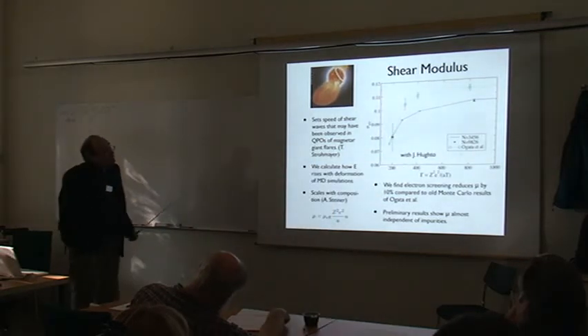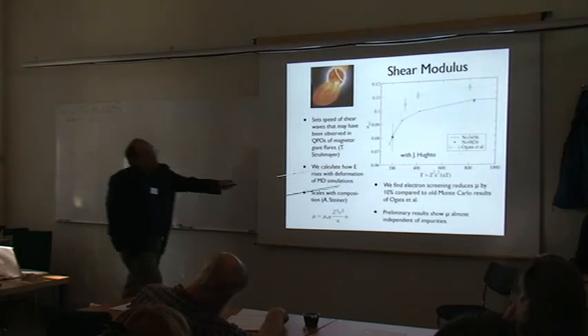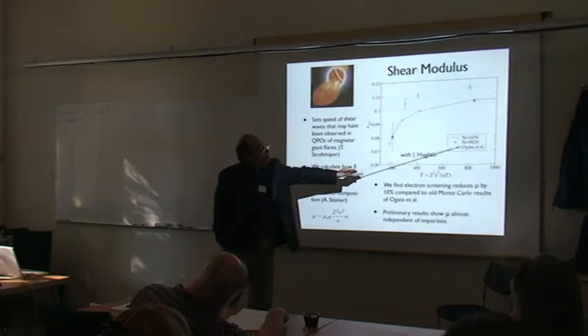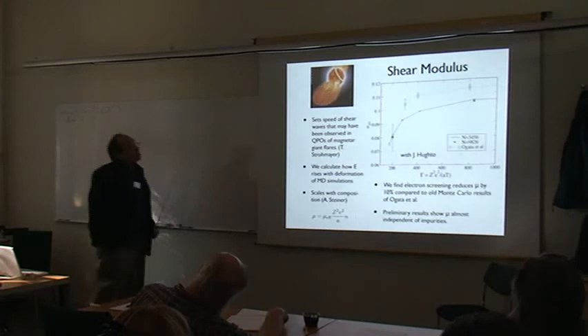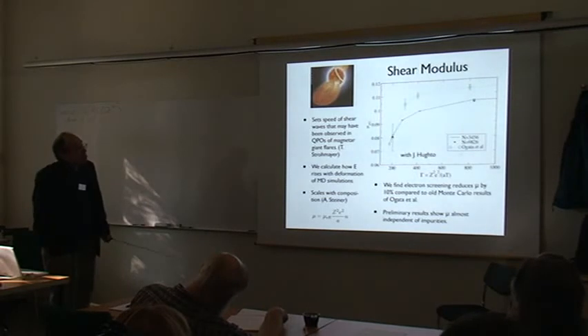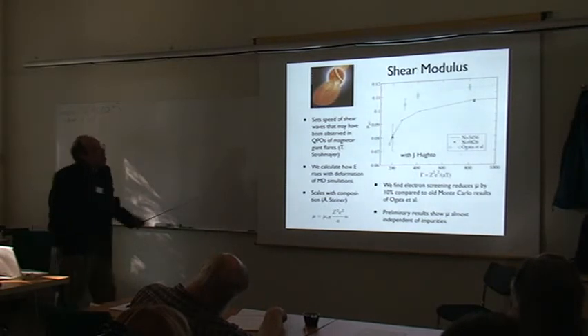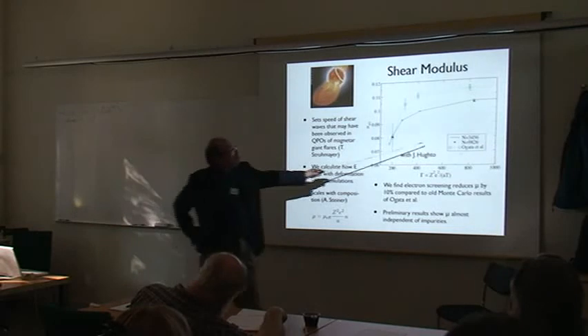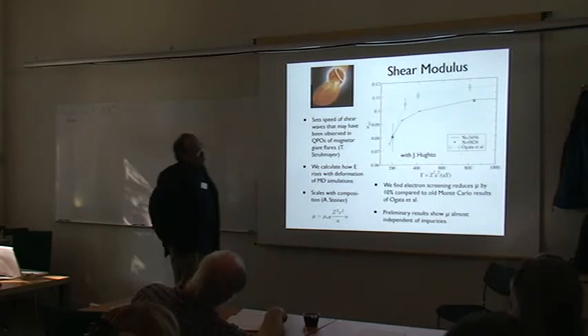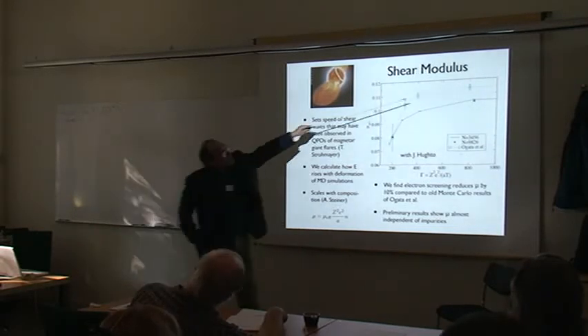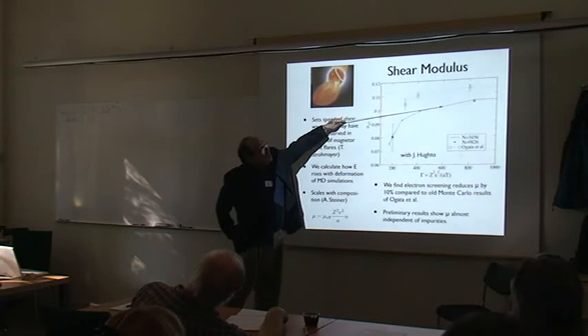So there - the older Ogata et al., these are Monte Carlo simulations of the shear modulus as opposed to molecular dynamics. Ogata et al. ignored the electron screening, and we find that electron screening reduces the shear modulus by about 10%.